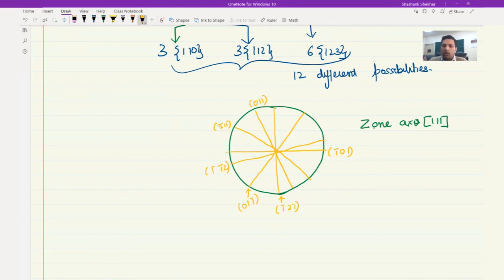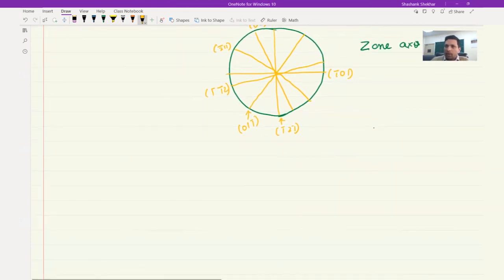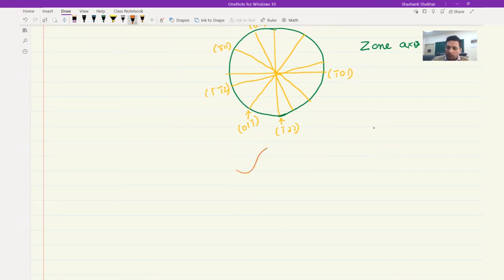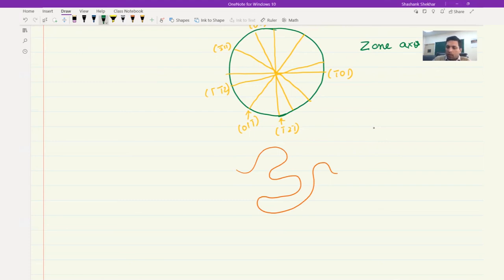Even from just six planes, you can see that a screw dislocation in a BCC system has so many possibilities. In the FCC system, a given screw dislocation had only two possible planes to move onto. But in BCC, with only {110} and {112}, you get six different planes. If you include {123}, there are twelve different planes onto which the screw dislocation can move. Because of this variation, the trace of a screw dislocation looks as if someone drew it by hand, and it is therefore also termed 'pencil' glide.